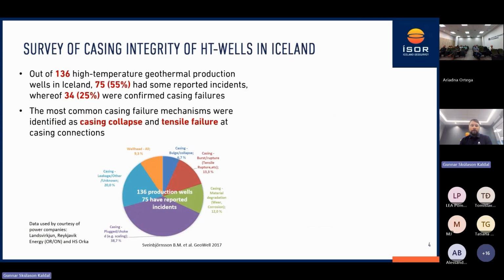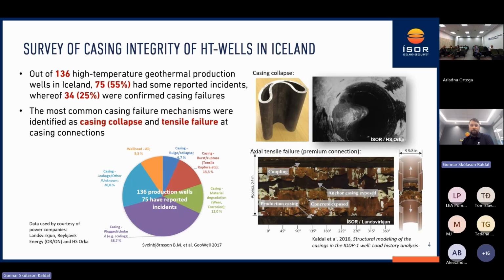We have done a survey of 136 Icelandic high temperature wells, where 75, or 55%, of them had some reported incidents. A quarter of those were confirmed casing failures. And we have found that the most common ones, as I mentioned, are casing collapse, the one above, and tensile failure, where the casing tears apart if it cools down after being in hot conditions.